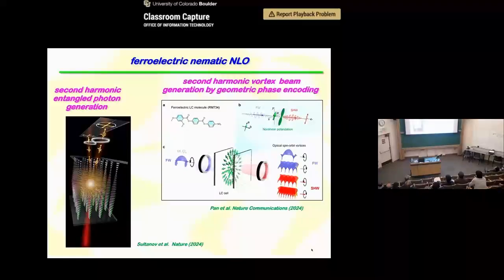Another application of nonlinear optics, ferroelectric nematic NLO, is that you can make a lot of interesting photonic devices with patterned films of liquid crystals. So if you pattern a radial pattern and shine light through this, you can generate, whether this were linear polarized or circularly polarized, a vortex beam. If this is a ferroelectric nematic, then you can generate a second harmonic vortex beam. So you can do nonlinear optics, and so the liquid crystal makes a nonlinear optical medium that can be spatially patterned.